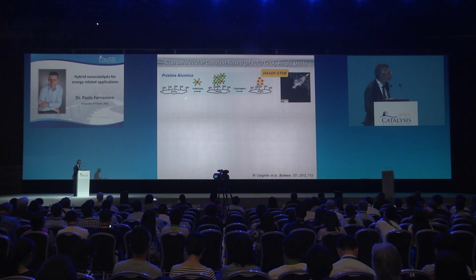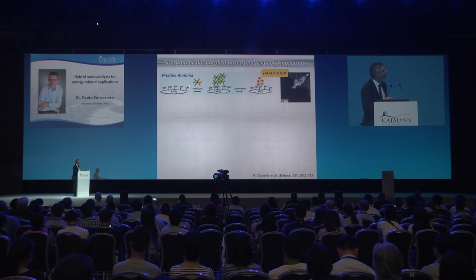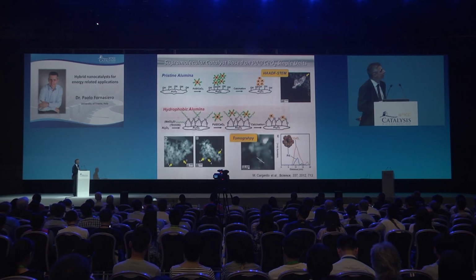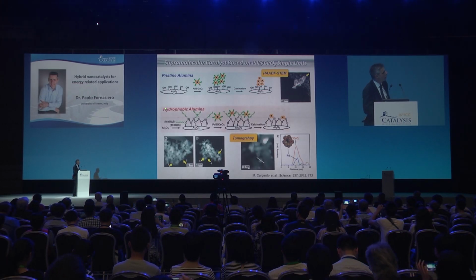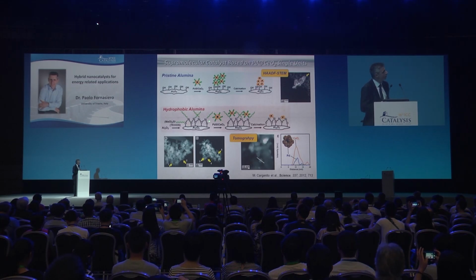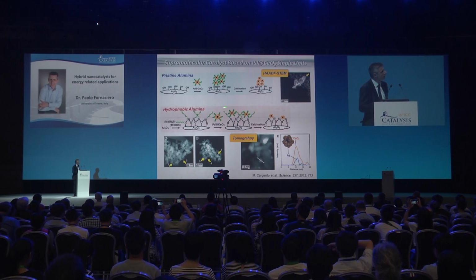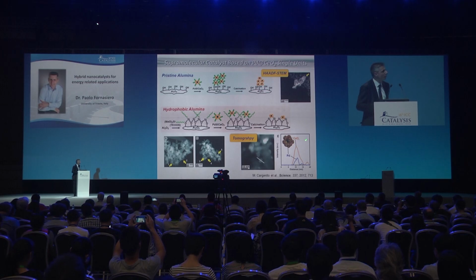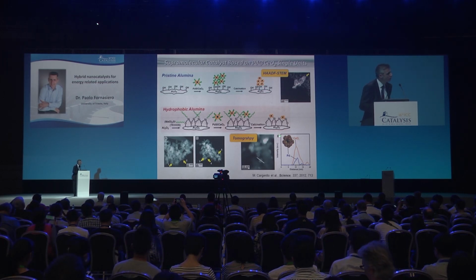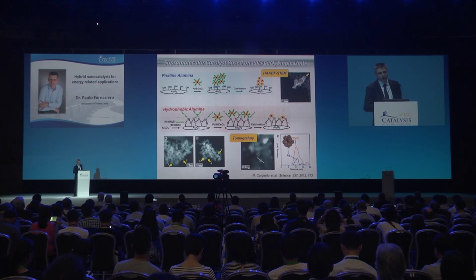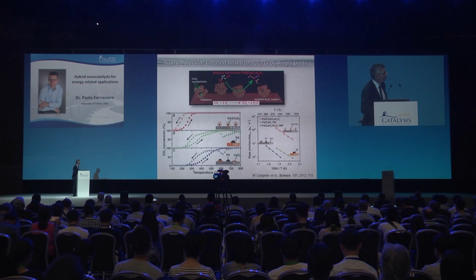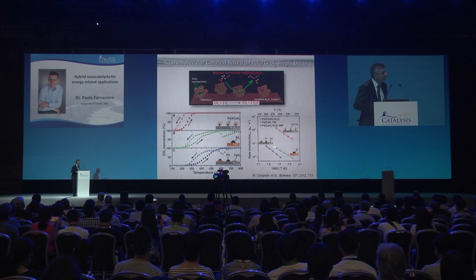Of course, you cannot use just a regular alumina or zirconia and so forth, because those are hydrophilic and our units are hydrophobic. So you have first to modify the material, making it hydrophobic by treatment with TEOS, for instance, and then having this organic stuff on the surface, you can really disperse homogeneously our units, and after calcination you end up with nicely homogeneously dispersed palladium-ceria units. And the performances of these catalysts are really good, as you can observe here in the Arrhenius plot with respect to the state-of-the-art catalyst.